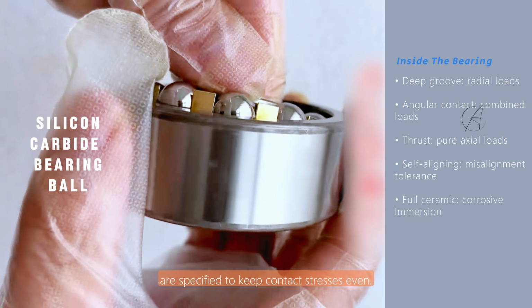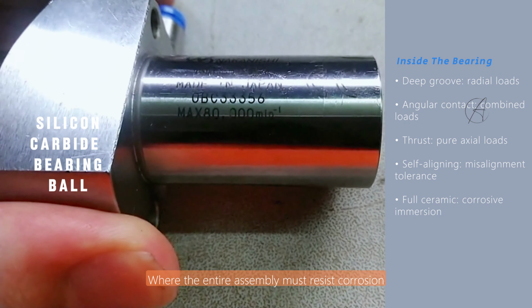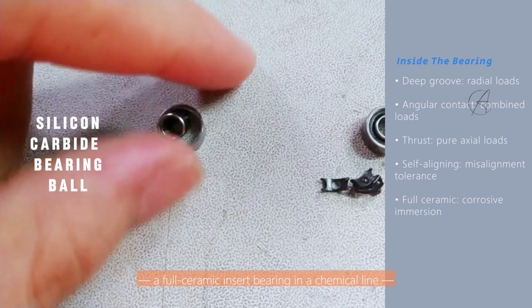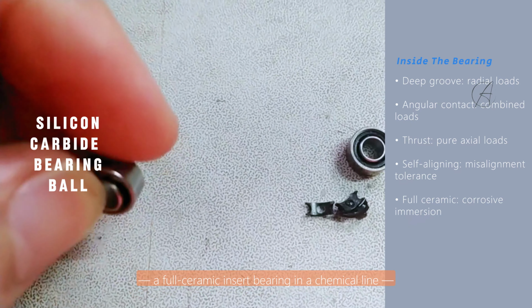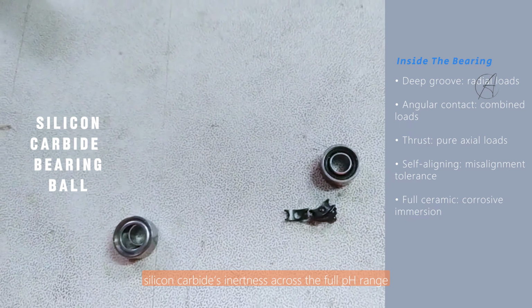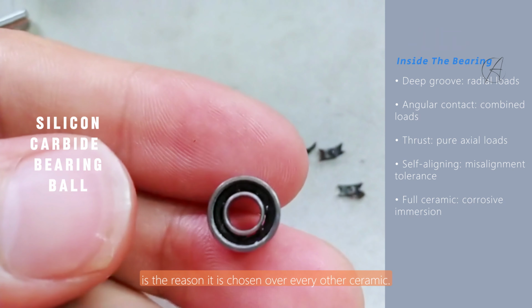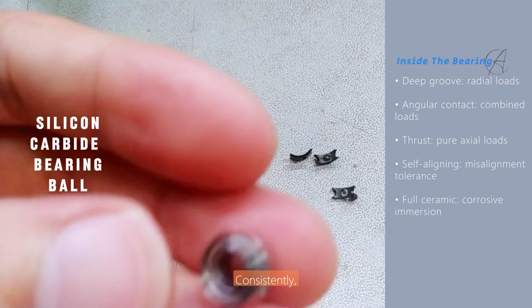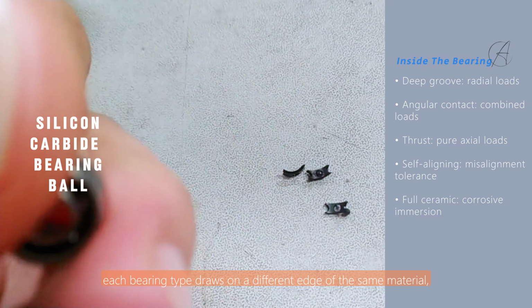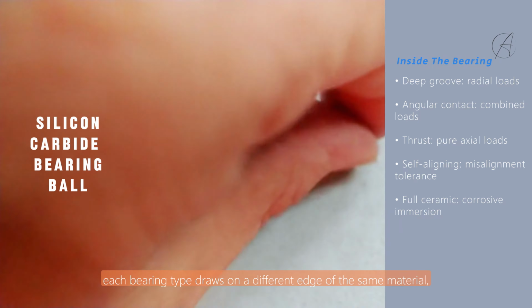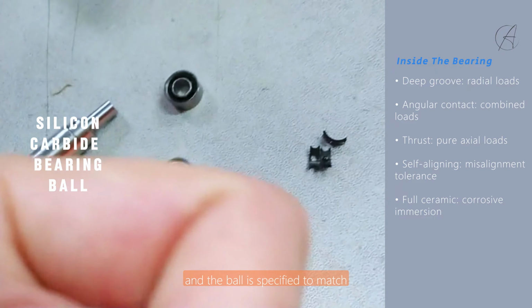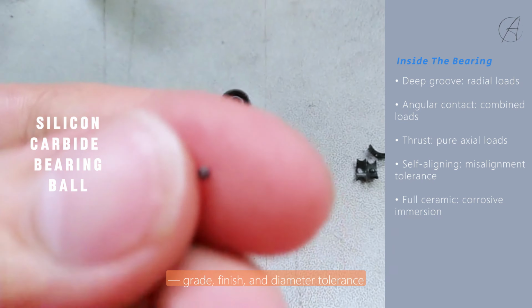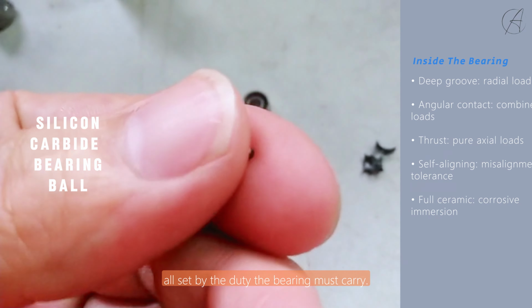contact stresses even. Where the entire assembly must resist corrosion, a full ceramic insert bearing in a chemical line, silicon carbide's inertness across the full pH range is the reason it is chosen over every other ceramic. Consistently, each bearing type draws on a different edge of the same material, and the ball is specified to match. Grade, finish, and diameter tolerance all set by the duty the bearing must carry.